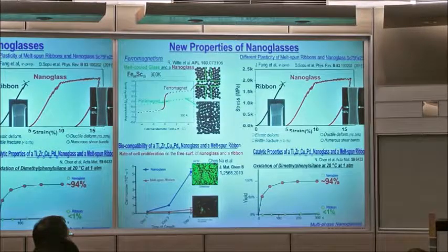And he finds a very large growth rate when the spacing between the gold particles is in the order of about 4 to 5 nanometers. And he gives an explanation in terms of molecular structure of the cell wall and the substrate. And it's about the same scale that we see here. And the reason why we used a titanium glass is because titanium is not a poisonous material.